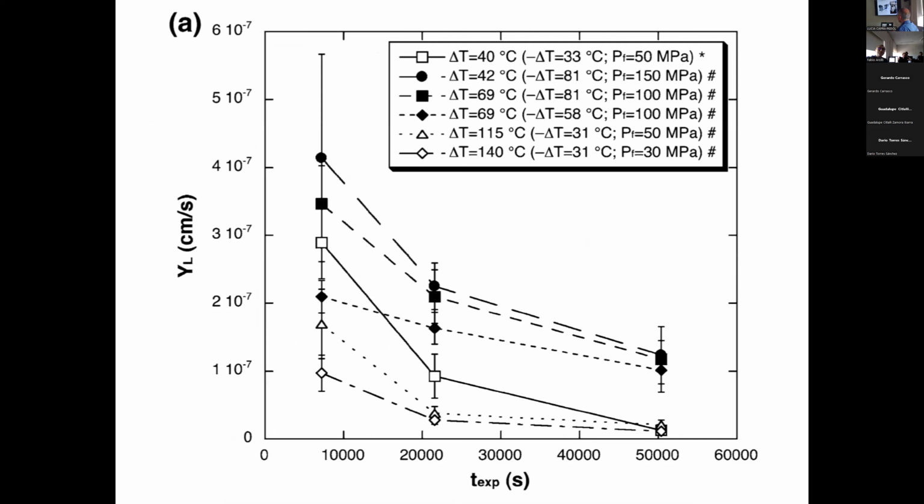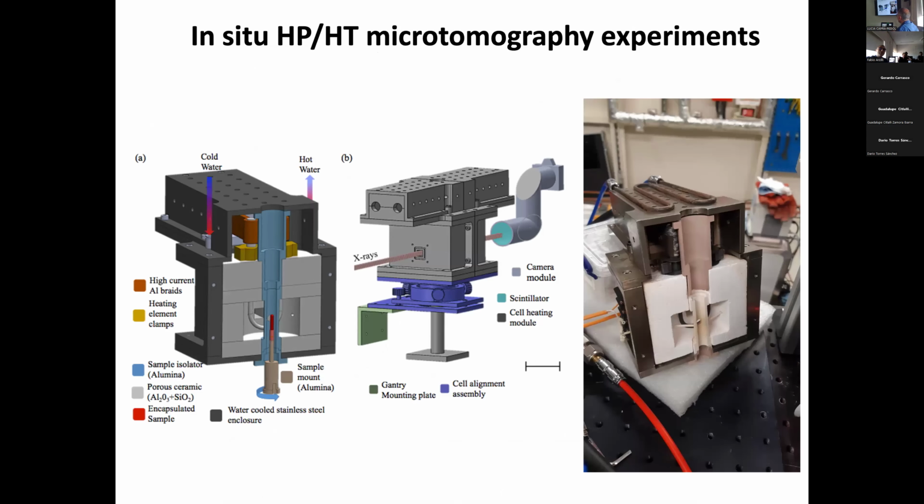Maybe I can introduce this now, because with Rafael, between 2016 and 2019, we performed several experiments with this furnace, Zali's furnace, an ambient pressure furnace. You can reach 1250 degrees Celsius. This is the heating element here. You have two thermocouples here, and the sample can be located here, basically within the furnace, close to the thermocouples.